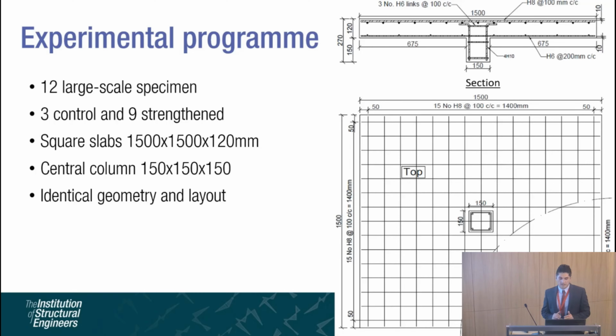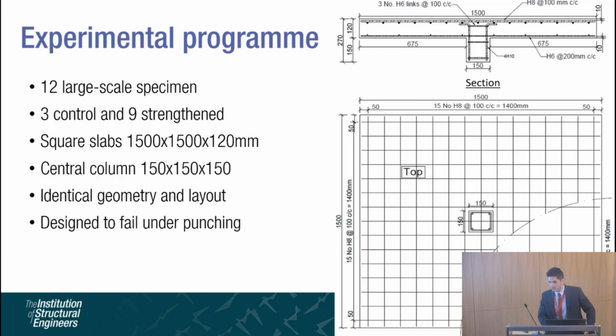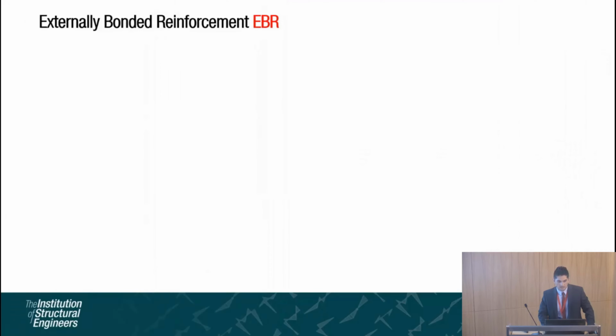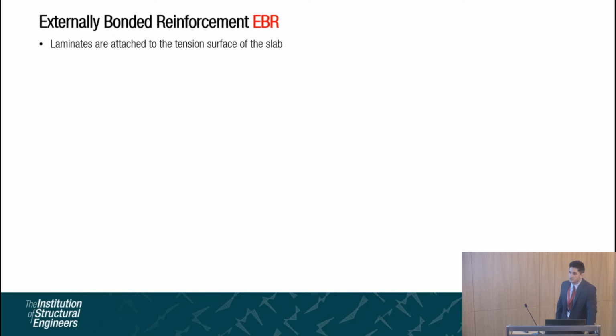All of the slabs have identical geometrical layout, and the reinforcement was similar. They were designed to fail under punching shear. We use 2 strengthening methods. The strengthening methods that we use are externally bonded reinforcement and near surface mounted reinforcement. In the externally bonded reinforcement method, FRP laminates are attached to the tension surface of the slab using epoxy adhesive. And these are basically acting as flexural reinforcement, which will indirectly increase the punching shear capacity of the slabs.